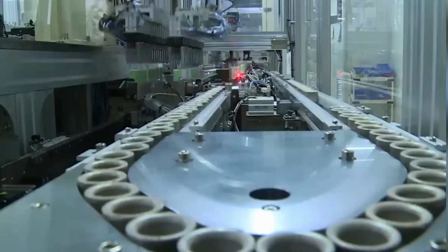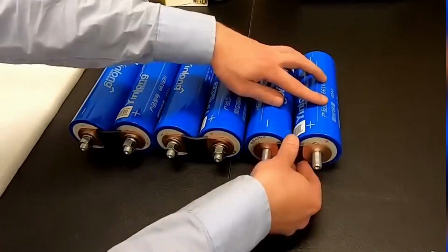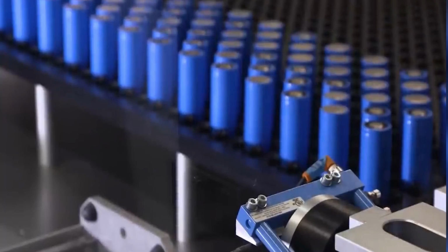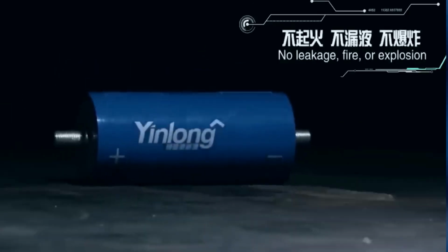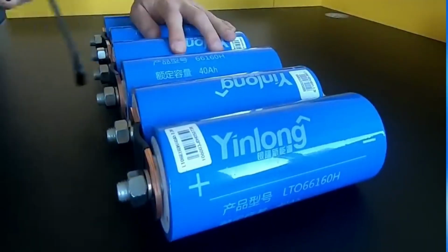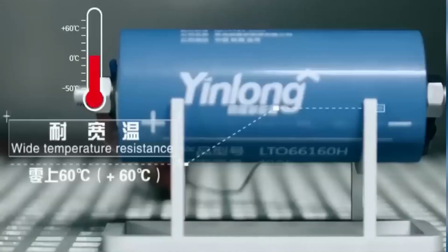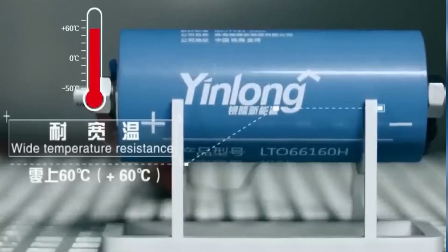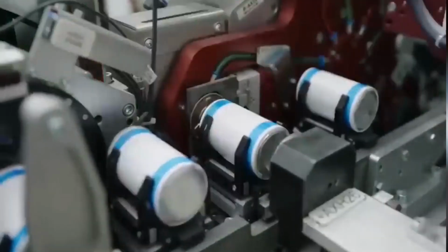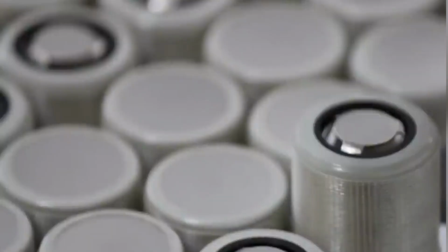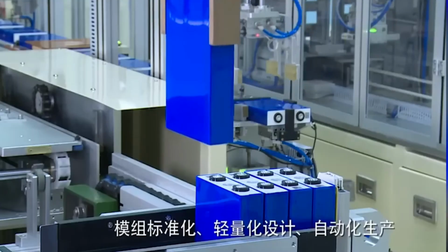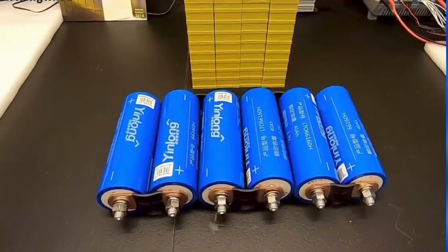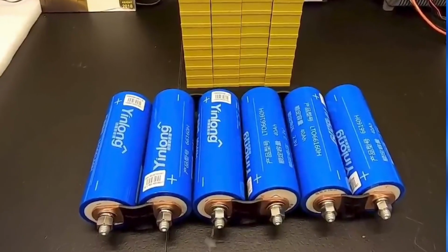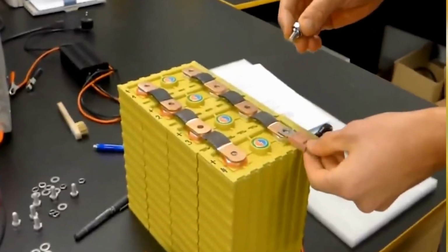Additionally, LTO batteries stand out in the realm of traditional energy storage, thanks to their remarkable low-temperature performance. By harnessing nanotechnology, these batteries can retain up to 80% of their full charge capacity, even at bone-chilling temperatures as low as minus 30 degrees Celsius. In fact, their operating temperature range is quite impressive, spanning from a frigid negative 50 degrees Celsius to a scorching 65 degrees Celsius, all while maintaining little loss in capacity or performance.